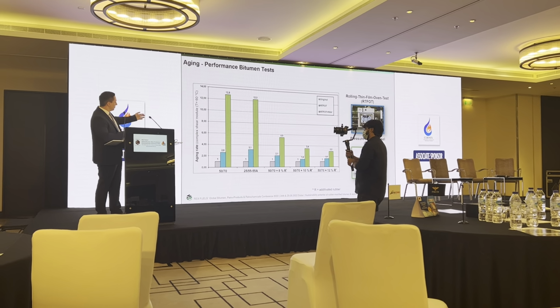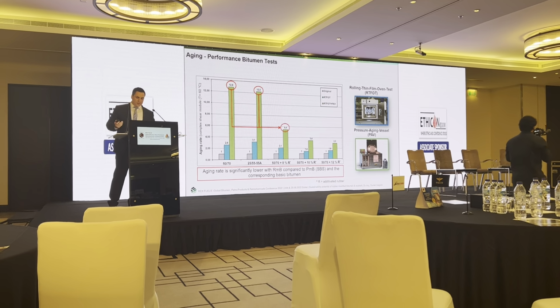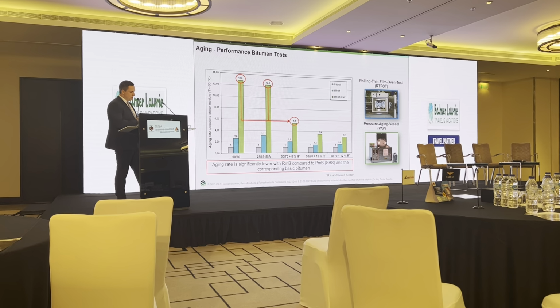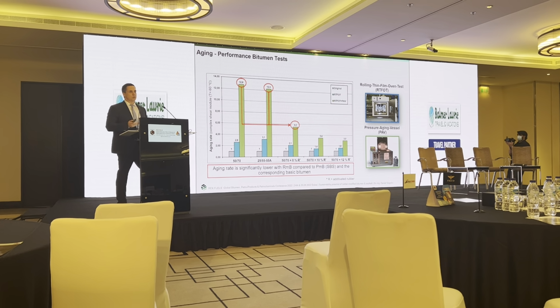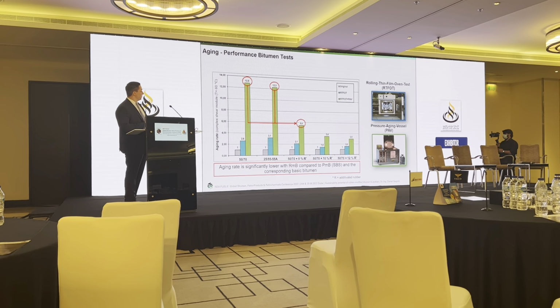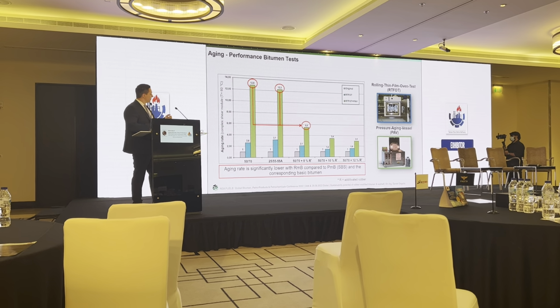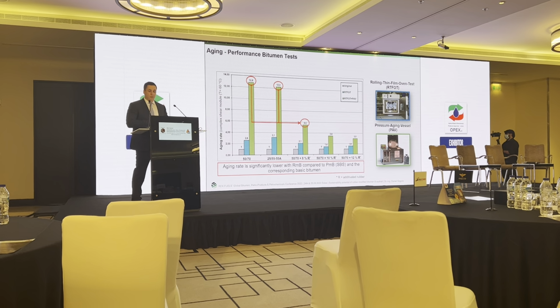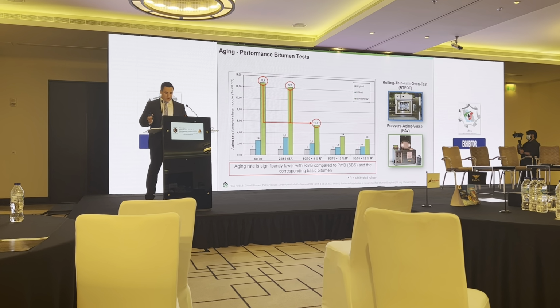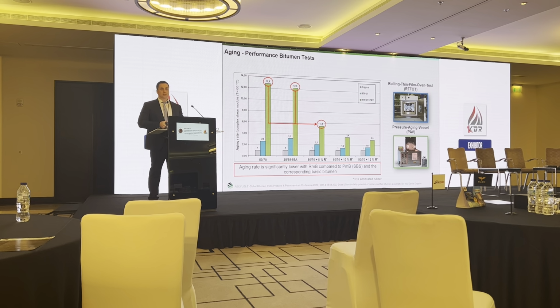So we are looking at the factors. Here it becomes obvious that the standard bitumen is aged by the factor 12.8 and the PMB by the factor 12.3. The same. In contrast, the 50-70 with 8% activated rubber is just aged by the factor 5.5, also half. So the aging rate is significantly lower with rubber modified bitumen compared to PMB and the corresponding basic bitumen or standard bitumen.